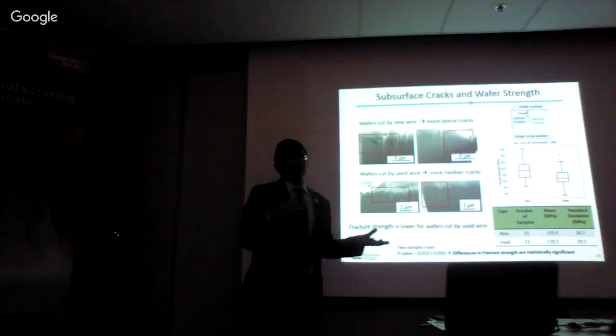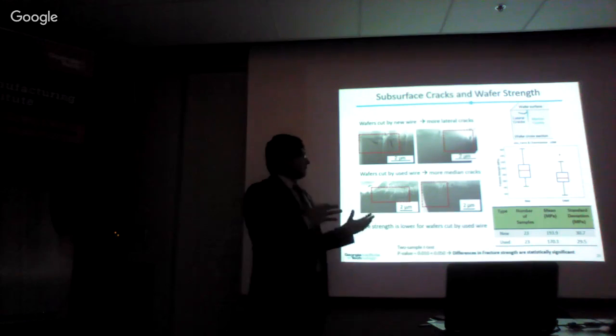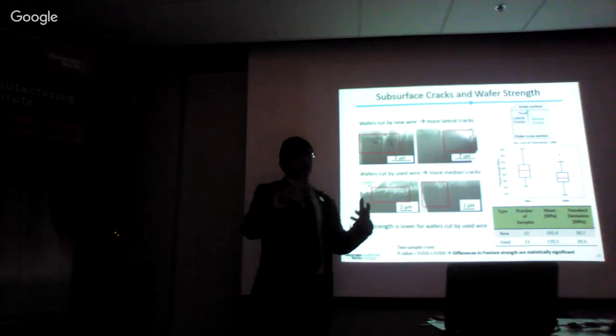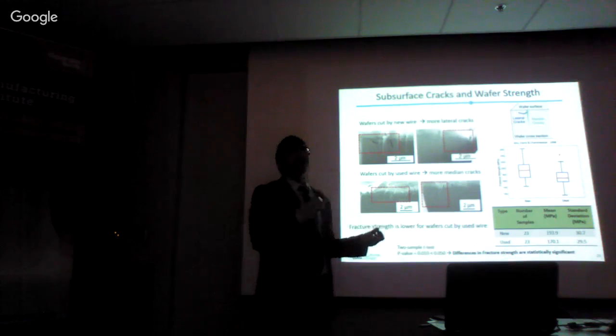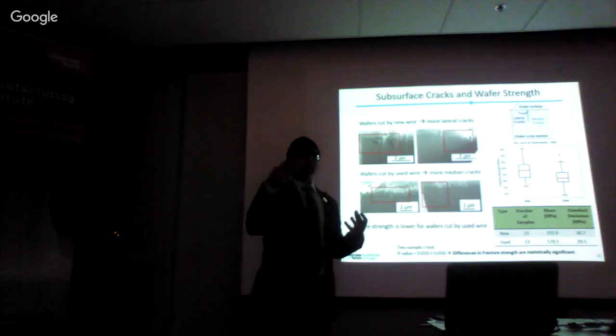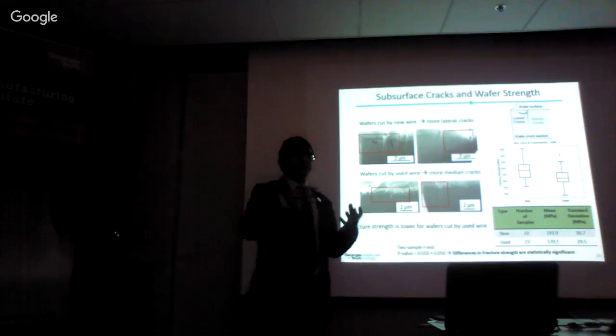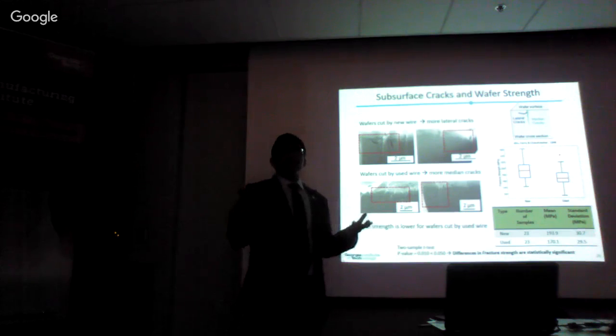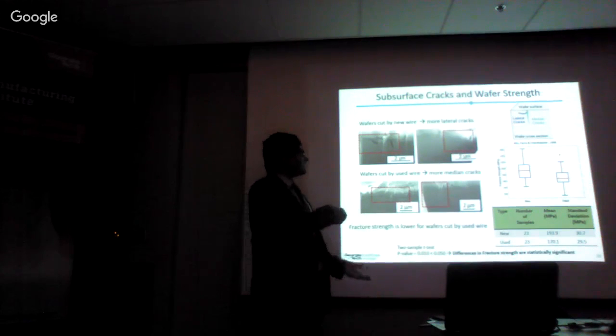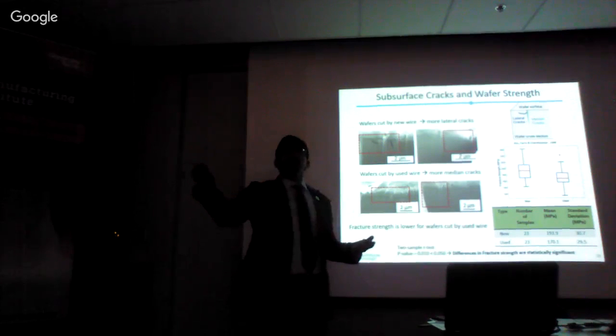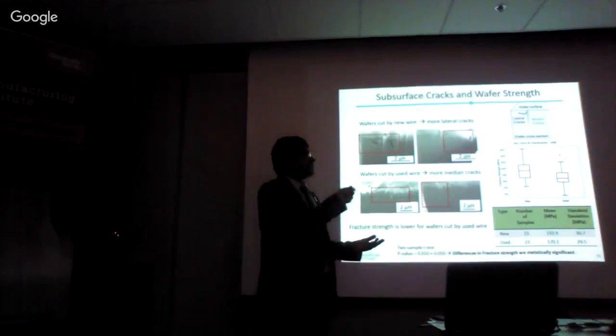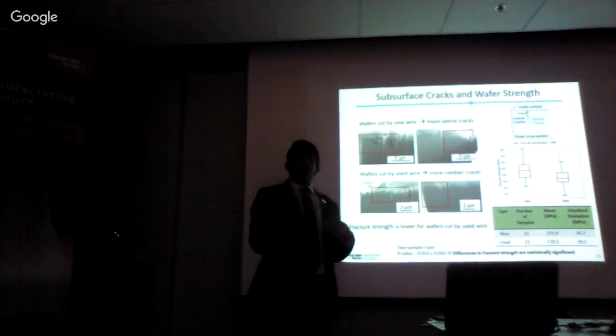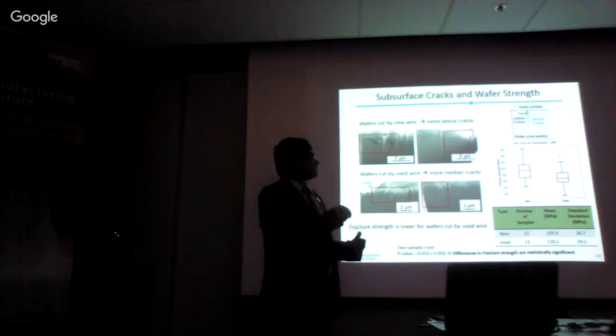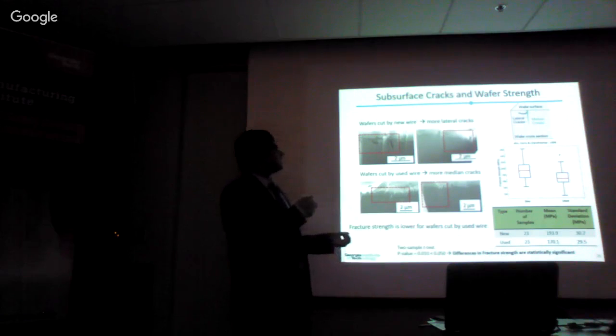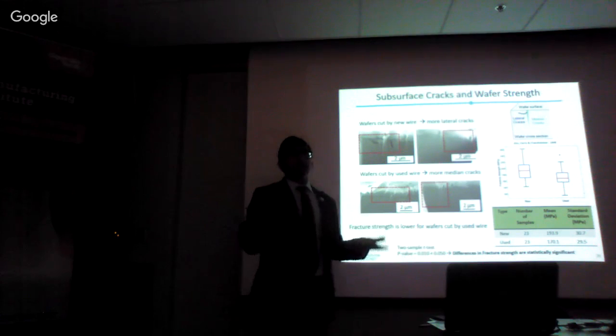The reason why this is happening, we hypothesize, is the difference with where some of the abrasives are getting lost, as we see there, and the force on each abrasive is being uncontrolled. Some of the abrasives are getting very high forces, and because of that, median cracks are being formed when the wafers are cut by the used wire side. That causes more median cracks compared to lateral cracks, which we see in the wafers cut by the new wire side. And that causes the fracture strength to be lower for the wafers cut by the used wire side.